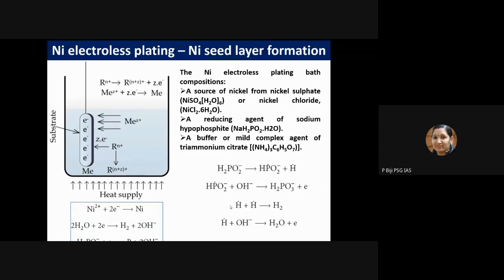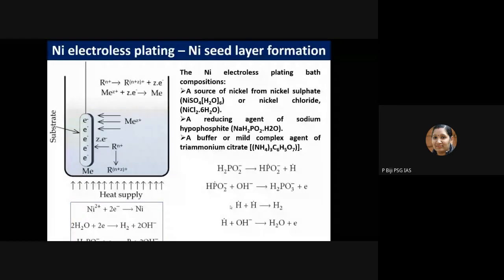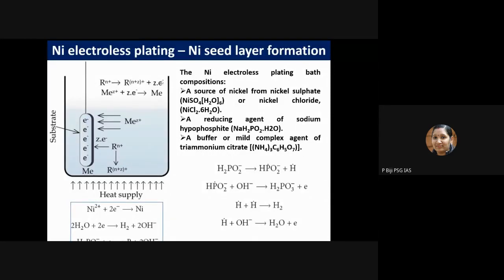Basically, the reducing agent undergoes oxidation, as you can see in this schematic of the general equation, producing some electrons. Those electrons will be given to your substrate, which is already activated. The metal precursor ions, in the case of nickel, nickel 2 plus, will diffuse towards your activated surface, and the electrons deposited by your reducing agent will be taken by the nickel, and it will be reduced into metallic nickel. So that's how the deposition happens. That's nickel electroless plating, seed layer deposition.